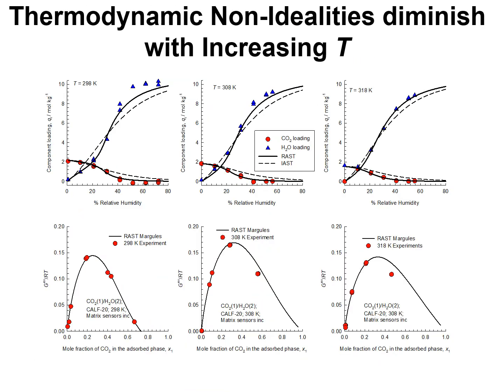Using the thin film approach, the mixture adsorption equilibrium was also determined at higher temperatures of 308 Kelvin and 318 Kelvin. The experimental data for water loadings, indicated by the blue triangles, and the CO2 loadings, indicated by the red circles, are compared with the estimates of the IAST. And we note that with increased temperature, the deviations of the experimental data from the IAST estimates are progressively reduced. In other words, thermodynamic non-ideality effects are of decreasing importance with increased temperature.